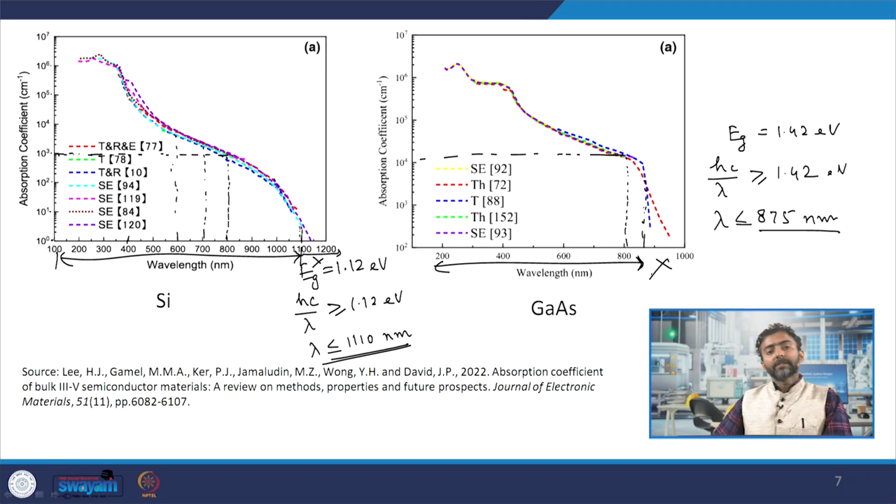So, that is a little bit of insight on the absorption coefficient, and it gives us some insight on how to decide the depth of the solar cell. I want to have the depth of the solar cell such that in the useful spectrum range, where the wavelengths have sufficient energy to raise the electron to the conduction band, those wavelengths should be sufficiently absorbed. And we can always do this simple calculation to check what is the depth by which, let us say, 90% or 99% of the useful radiation can be absorbed.